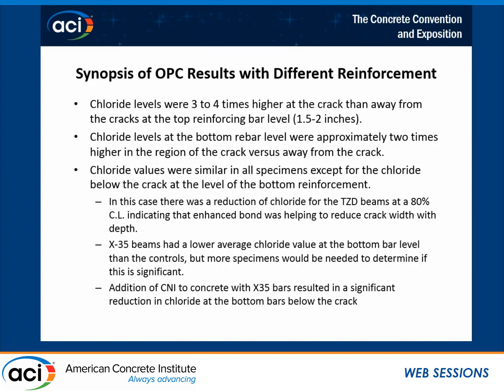So definitely there's an effect of the crack, and the crack is a severe way of accelerating a corrosion test, but it also shows you how important cracks can be for modeling. Because once again, you're getting this chloride down there much faster than your model is going to predict.